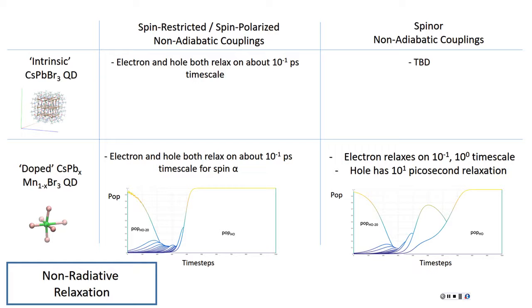And if you look at the Redfield tensors, the magnitude of the spinor transitions is about half of the spin polarized, which I'm not really sure why that is. Then it would be interesting again to understand the nature of this intermediate HOMO minus 1 state. Why is it so different? But if you make a comparison between spin polarized and spinor, and you're not showing the beta component, then you need a very strong argument. Oh, it's only for frontier orbitals, close to the HOMO.